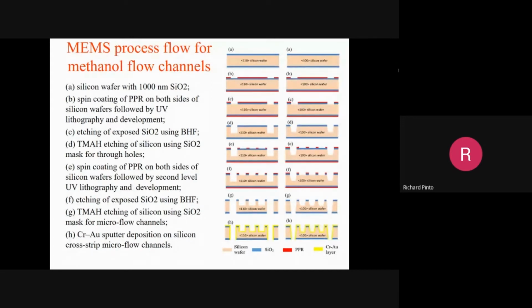Now we start with a silicon wafer. You can start with 100 or 110. Left side is 110 and the right side is 100. We use silicon device technology. We grow oxide on silicon, then spin photoresist on both sides. Both sides are required because the backside has to be protected from etching, oxide and silicon. Now silicon is etched using tetramethyl ammonium hydroxide, TMAH, which is a very famous etchant, using silicon dioxide as a mask.